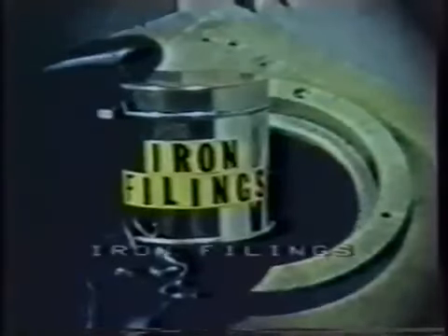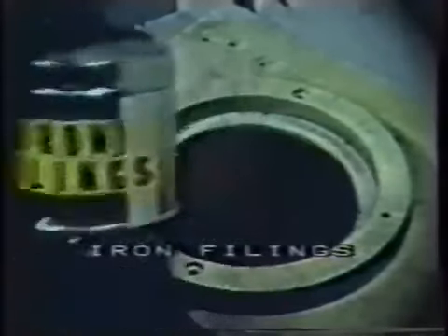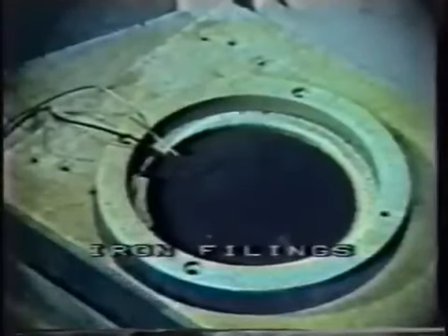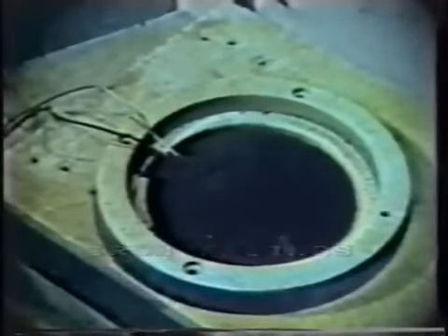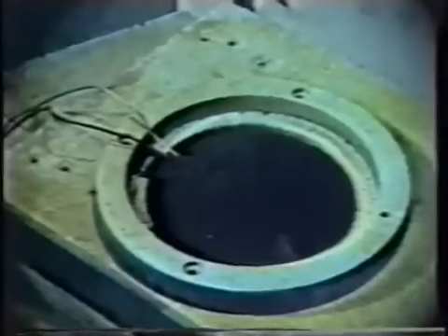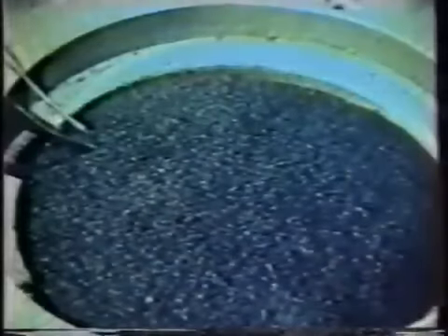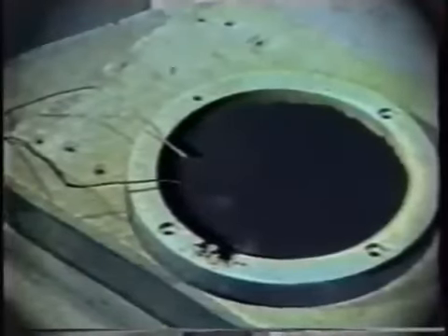As you might expect, this is a big disappointment to us. We were hoping that these materials would be very effective. We even tried iron filings to see if that would be a better way of removing the heat. Again, it wasn't quite as spectacular as the copper, because it was already black, and the fire continued to burn underneath it. The iron filings were totally ineffective.